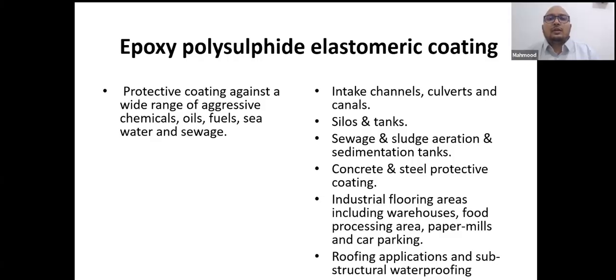And epoxy polysulfide elastomer coating. Even though epoxy by nature is rigid, okay, to make it a little flexible, because the main intention of the coating is to provide waterproofing. Concrete is rigid, epoxy is also rigid, but you need to provide waterproofing, and you need to provide crack accommodation. It should accommodate the movement of the structure.